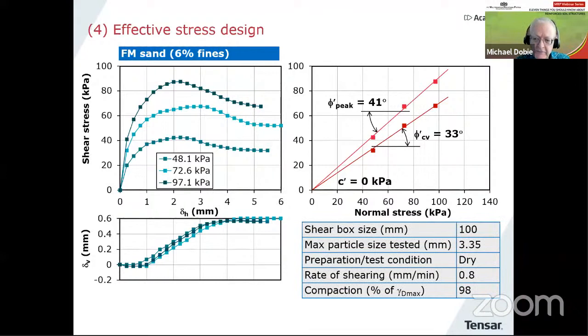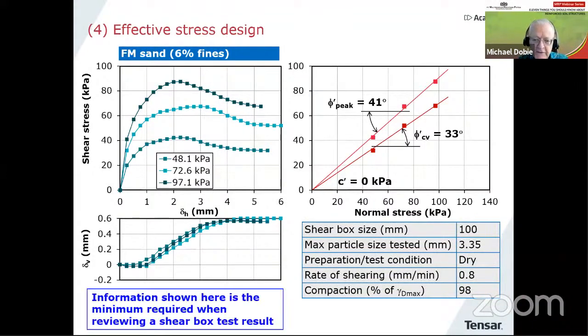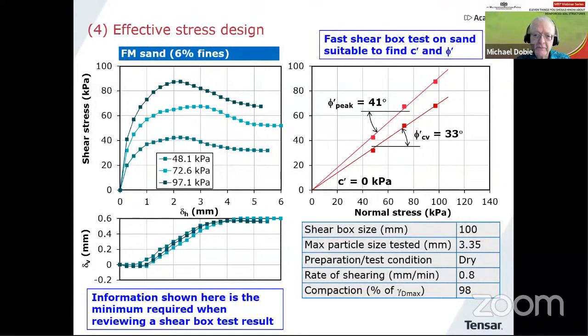And then I've got a little table down here with some important information. And in fact, that information in that box, plus the diagrams, is the minimum information you require to make an assessment of a shear box test. And this test is very adequate to give you C dash and phi dashed for a sand like this. And one of the really important things to notice here, it's a fast shear test, and the rate of shearing was 0.8 of a millimeter per minute, perfectly acceptable for a sand.